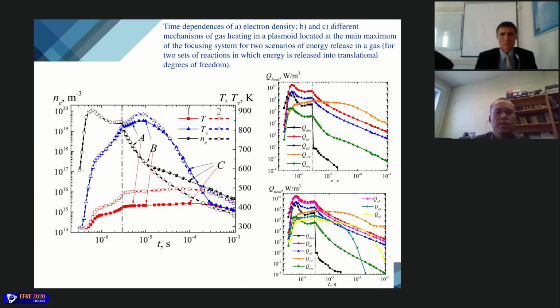After the end of the active phase of the pulsed discharge, the vibrational temperature of nitrogen continues to increase in the time interval from 3 microseconds to 10 microseconds, to 850 kelvins for the first set of gas heating mechanisms, and up to 880 kelvins for the second. And then it begins to decrease in the time interval from 10 microseconds to 1 millisecond. Its values drop to approximately 400 kelvins respectively.